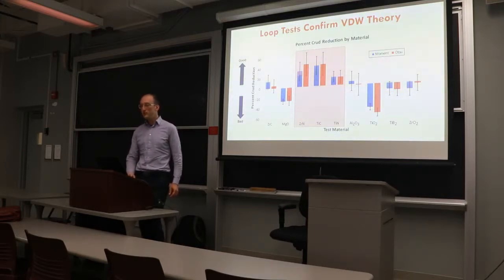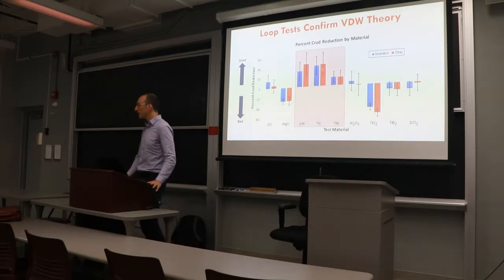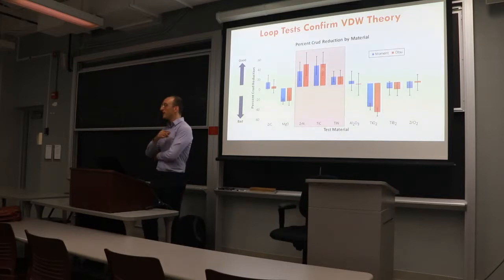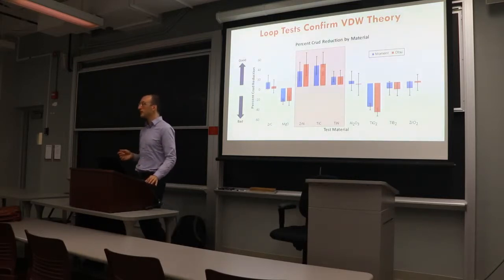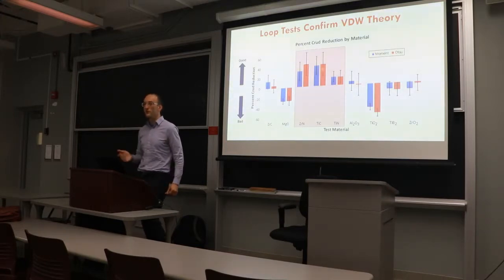So we know that these resist crud, at least these two resist crud pretty well. And they've got to be stable in high temperature, high pressure water. So these should be pretty good in terms of moving to the next stage for a lead test rod. We've also had these coatings in the MIT reactor for half a year in a flowing PWR loop. We're currently analyzing these coatings to see if they survive radiolysis. So that's another binary yes or no question.